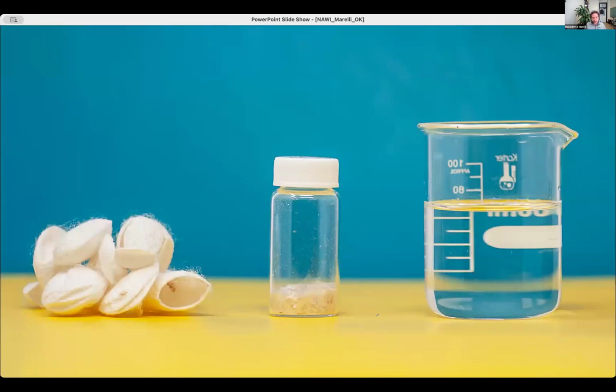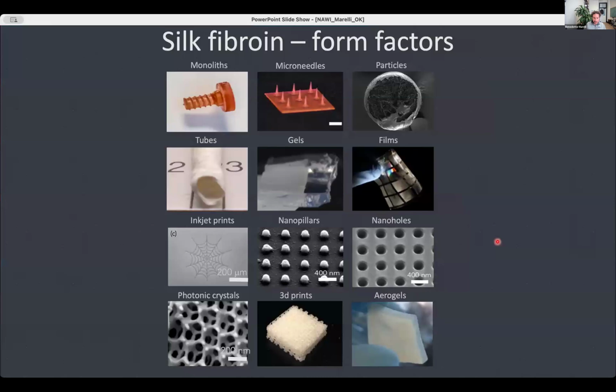So the material that my lab typically uses is silk. We don't start from the silk that you consider a highly expensive textile silk. We use the silk that comes from the waste of silk. The fiber itself can be deconstructed by removing the hydrogen bonds that keep the silk fibroin protein together. This can be done using a chaotropic agent that is able to disaggregate the hydrogen bonds of the beta sheet in silk. And the fiber itself goes back to what it is, as you can see here, a water suspension of silk. And then by driving the self-assembly again, silk from a fiber can become a technical material that can compete with synthetic materials to perform in a wide breadth of applications.